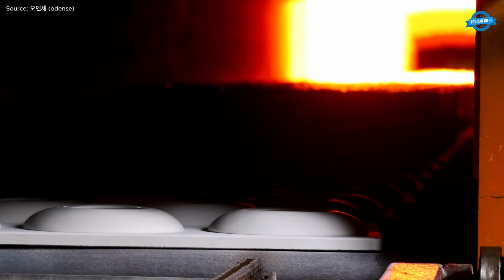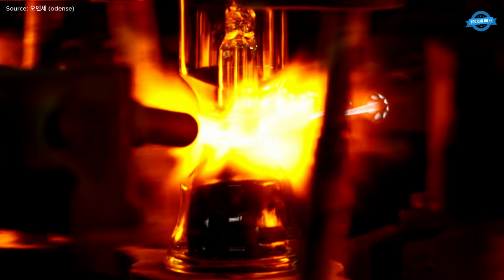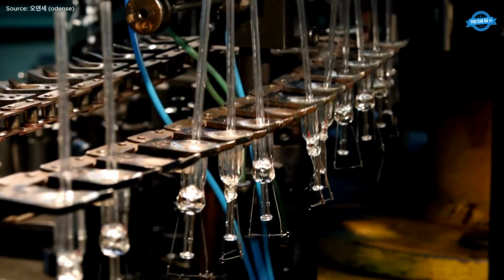Once the ceramic housing is completed, attention shifts to bulb fabrication. Glass components are formed and processed under controlled thermal conditions, with burner temperatures maintained between 560 and 580 degrees Celsius to ensure uniform glass flow and precise sealing. Vacuum generation is a critical step, with internal pressure reduced to a range of 0.002 to 0.008 millimeters of mercury, minimizing impurities and extending filament performance.